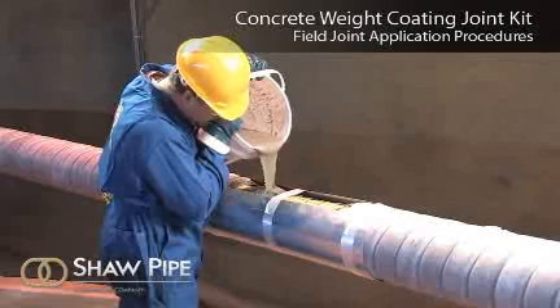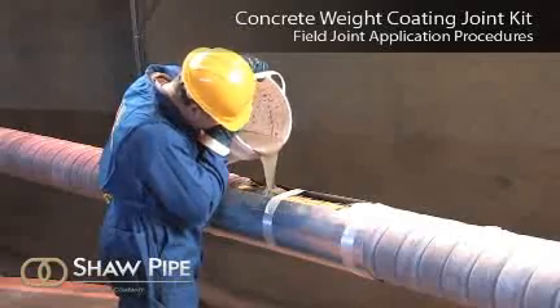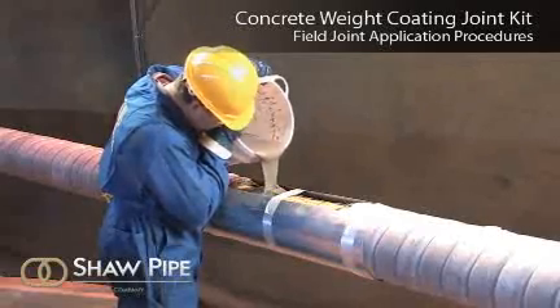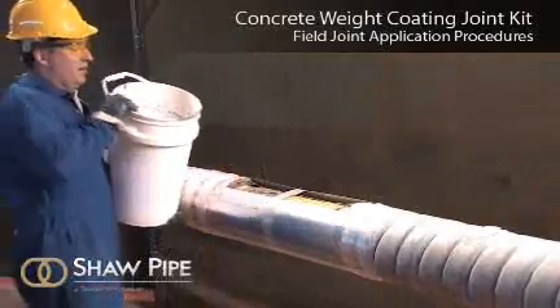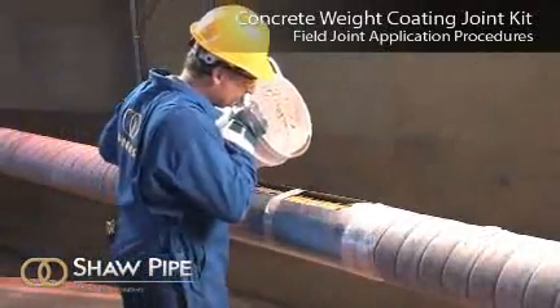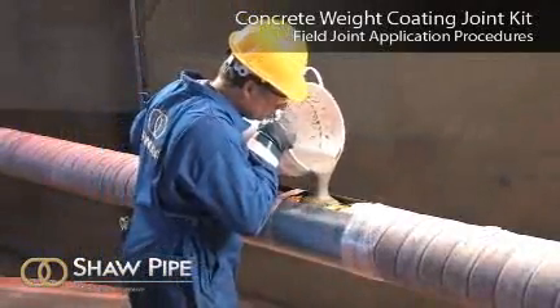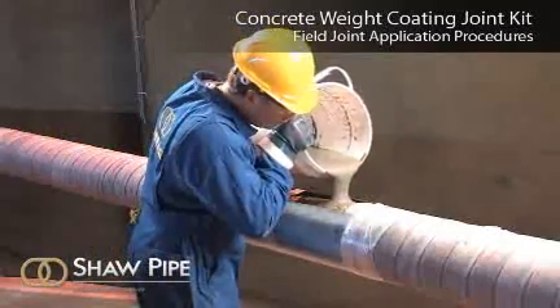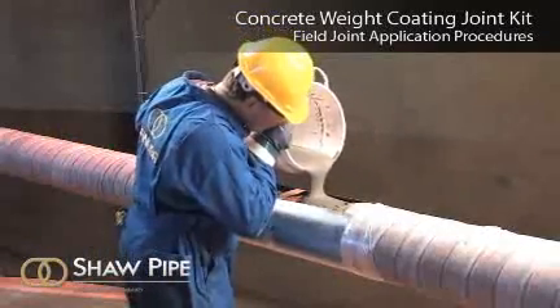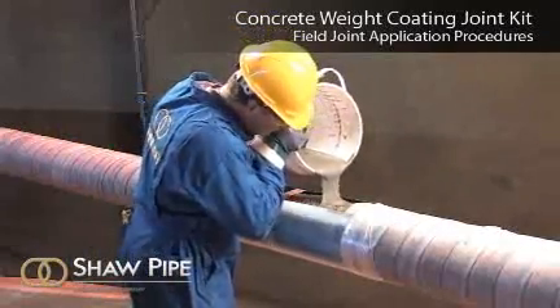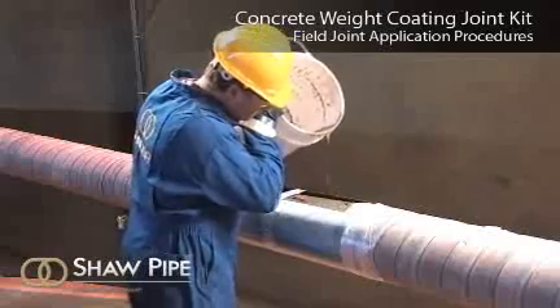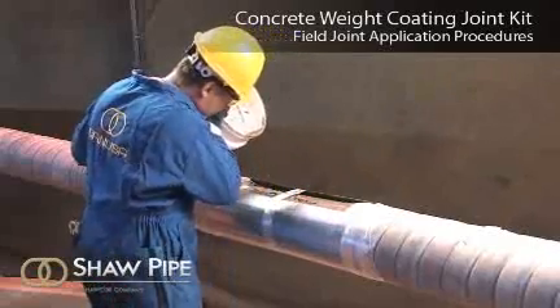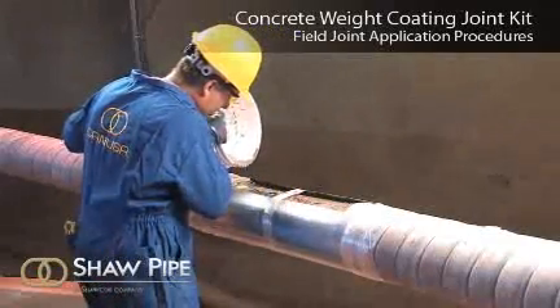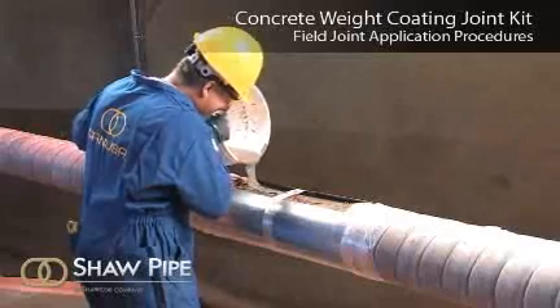Mix thoroughly until an even consistency is achieved. If a more fluid consistency is required, add more water and remix. The grout only has to be fluid enough so that it will flow uniformly around the joint area when poured into the forms. The fresh grout may be remixed for a period of up to 1 hour after the initial mixing, after which time it should then be discarded.